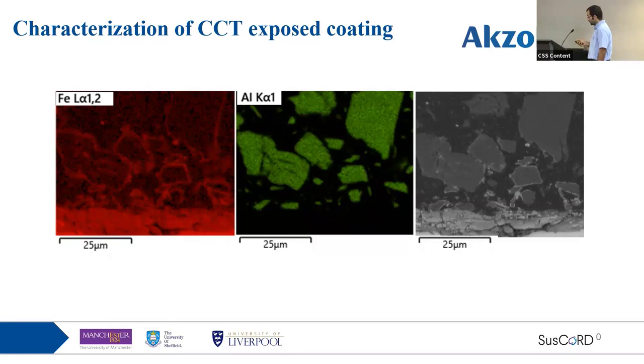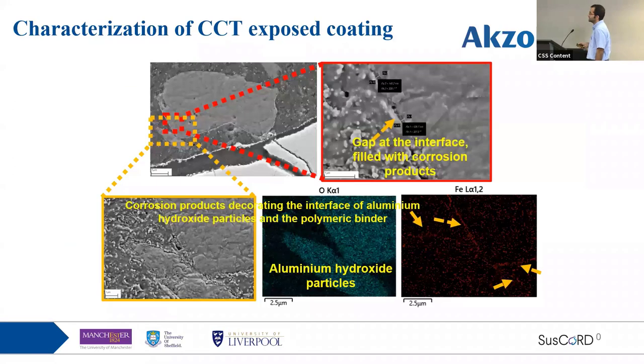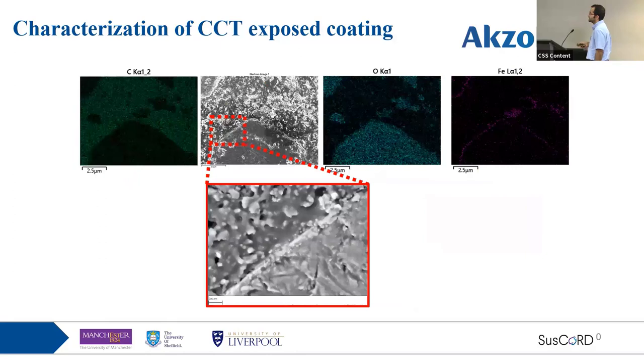So I tried to look into more detail at these closed regions. As you can see here, corrosion product is already deposited at this interface. And if I increase the magnification, I can see a gap exists, which is in the range of 100 nanometers. And actually, it is filled with corrosion product. But there are also other cases.